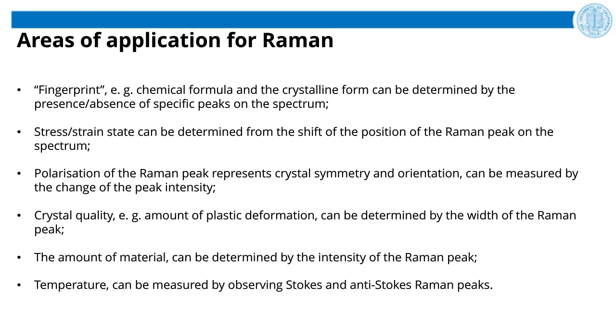Generally, Raman spectroscopy is sensitive to the chemical bond type of a material, and everything that somehow affects the bond can be studied with Raman. That is why the following information can be received from Raman spectroscopy. First of all, it allows us to determine the chemical compound or formula by the presence or absence of specific peaks on the spectrum, and we call it a fingerprint technique. It is important that characteristic Raman frequencies, or peak positions, are representative not just of the chemical compound of the material, but also its crystalline form. For instance, between different mineral forms of titanium dioxide, Raman can distinguish which one of three different mineral forms was probed, for example, anatase, brookite, or rutile.